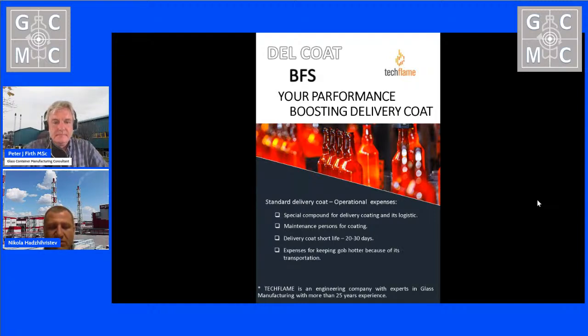And not in the last place, it is expenses for keeping gob hotter. What does it mean? During the transportation, your gob temperature is going down. And if you measure your gob temperature at shear level and compare the temperature down, it will be with a difference of minimum 2 to 3 degrees. You can say it is 2 to 3 degrees. For blow and blow, no problems at all. But for NNPB, it could be a problem. And then you should put more gas to keep glass hotter.